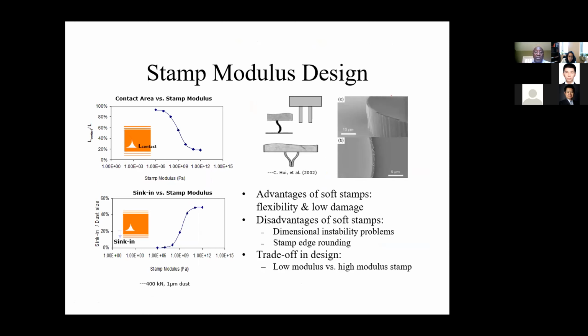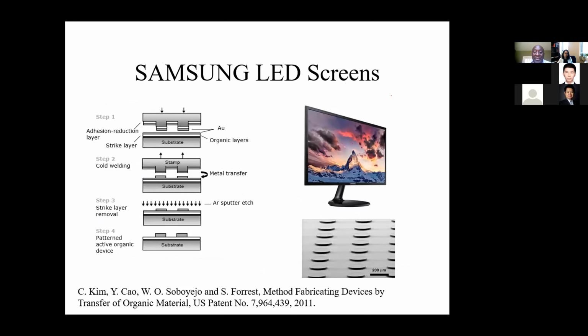What you have to do is to model the contacts as the stamps fold around the defects and look at the nature of those contacts and the sinking due to the defects in a way that allows us to optimize the process. The outcome of all this was a patent, which was issued in 2011, the patent for the OLED screen processing methods. And I have to say, it came from a collaboration with Steve, with whom I shared an office when I first went to Princeton. And so it's been licensed by Samsung, and it's a patent that's been generating some income for the last few years.